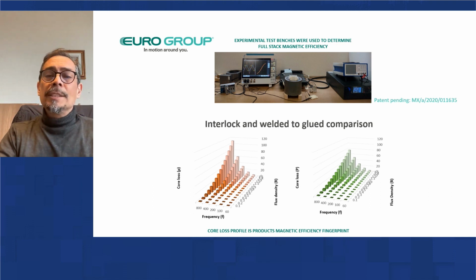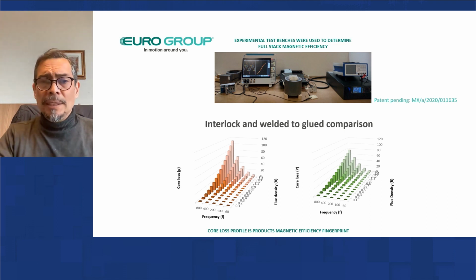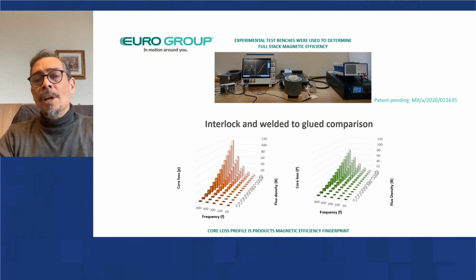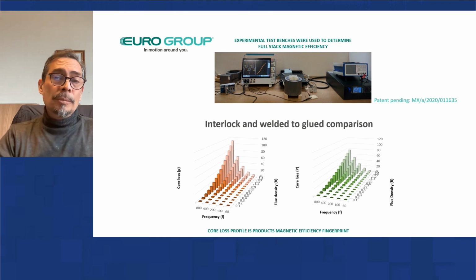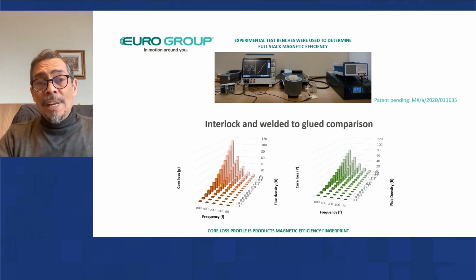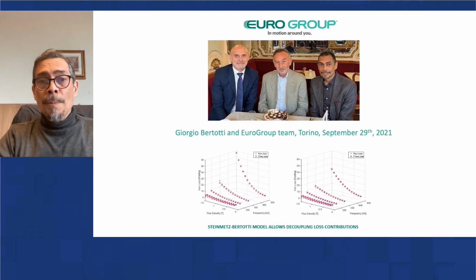And the same lamination was glue bonded on the right side in green. And then you can see that the energy losses shown in this graph are very much reduced. We are speaking about, in this example, 44% less losses. That means a great amount of less heat, a great amount of less vibration and noise.